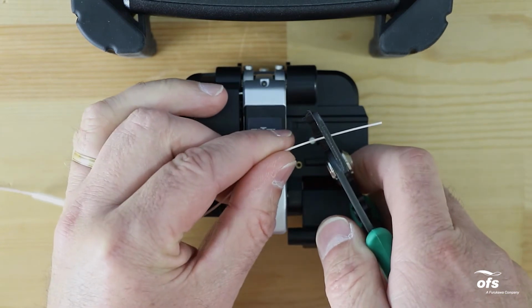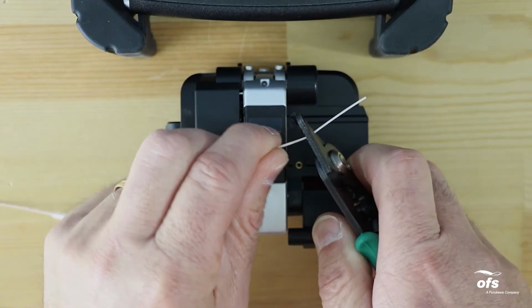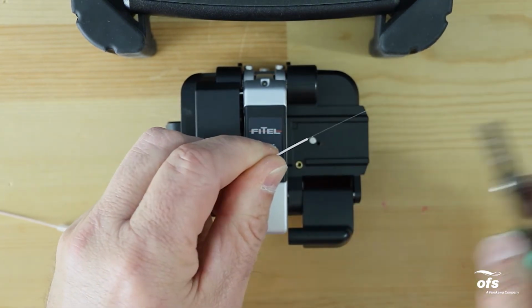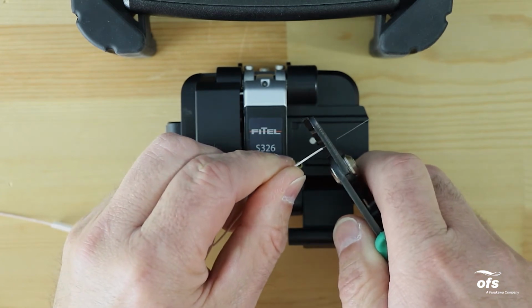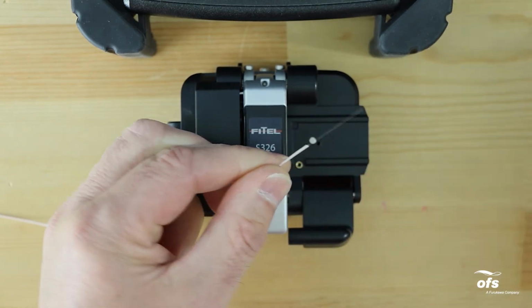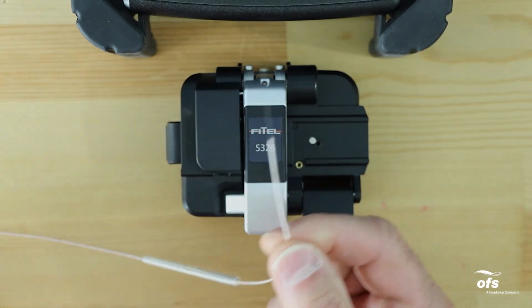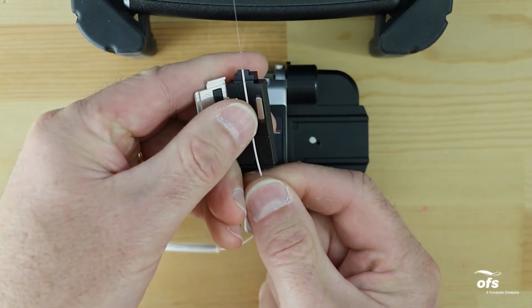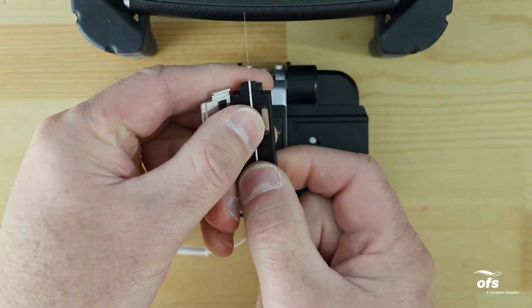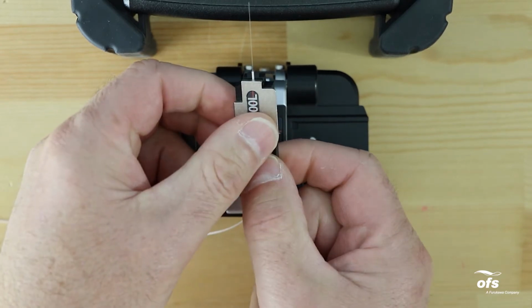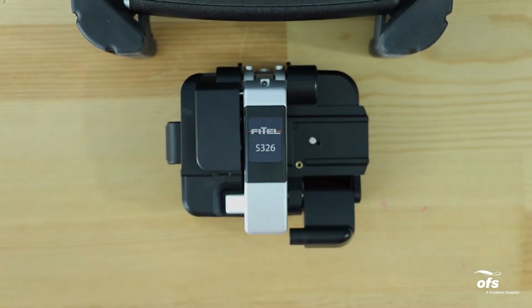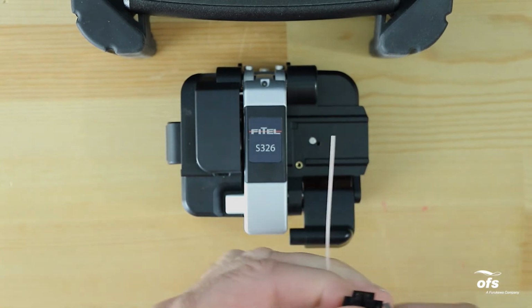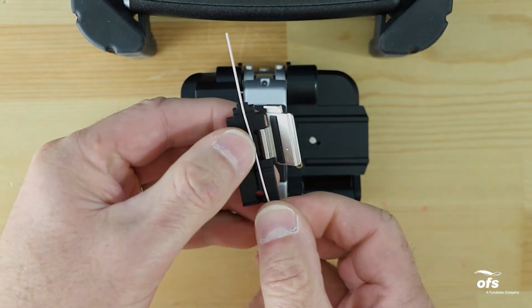If you are using 900 micron fiber coating, strip approximately 30 millimeters of 900 micron and 250 micron coating from the end of the fiber, leaving bare glass. Load fiber in a removable holder with the coating edge even with the end of the holder. Fiber curl facing down.